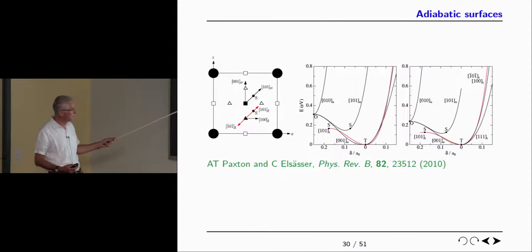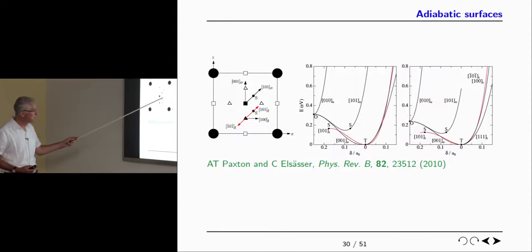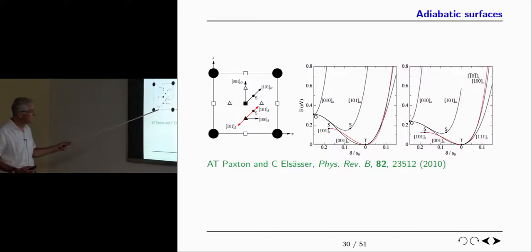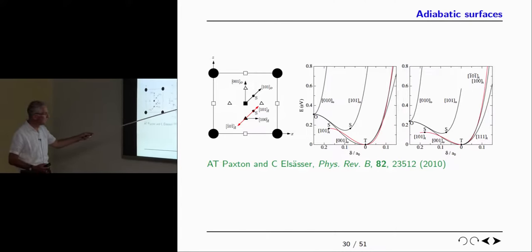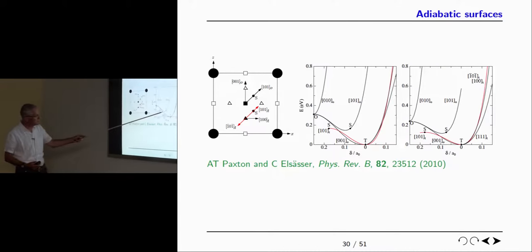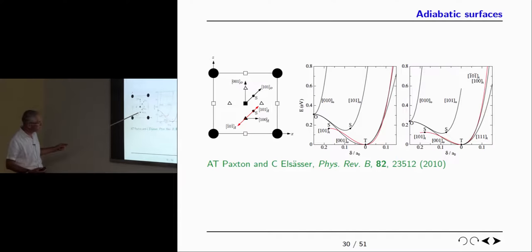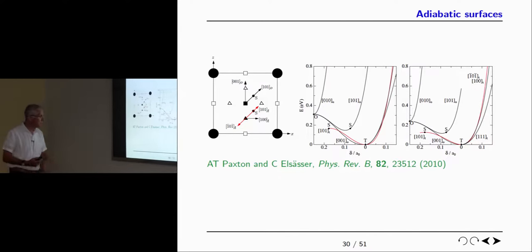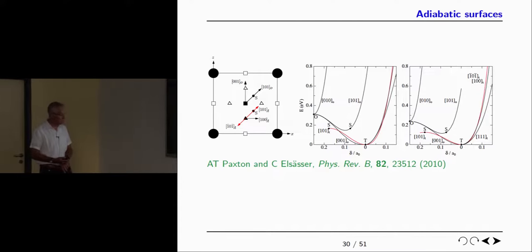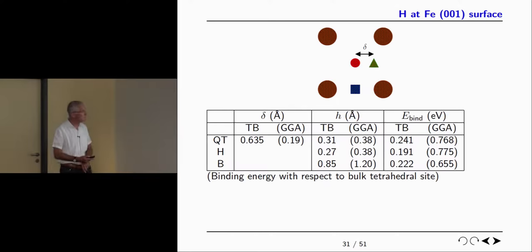So the most important one is because hydrogen occupies the tetrahedral sites in the BCC iron. These are the octahedral sites here. These are the iron atoms. And so you're particularly interested in this path, which might be the minimum energy path for this hydrogen atom. It goes through a saddle point and ends up in the neighboring tetrahedral site. That was this line I've drawn here in red. In point of fact, it doesn't quite go through the saddle point. As you can see, the minimum energy is slightly away from the saddle point. It actually takes a slightly curved path like that. And without any kind of fitting at all, the agreement with the density functional is extremely good. So it worked very well from that point of view.